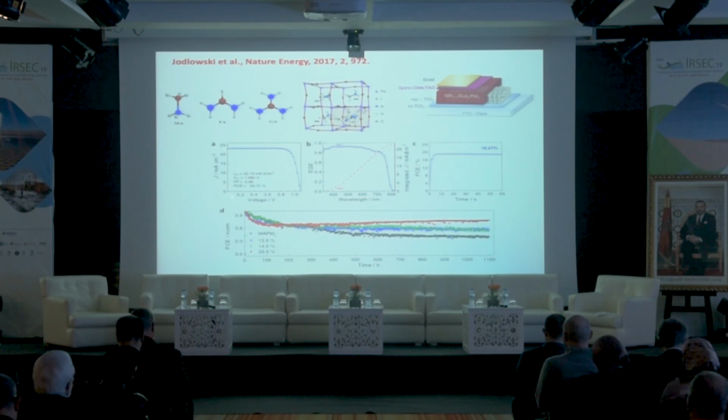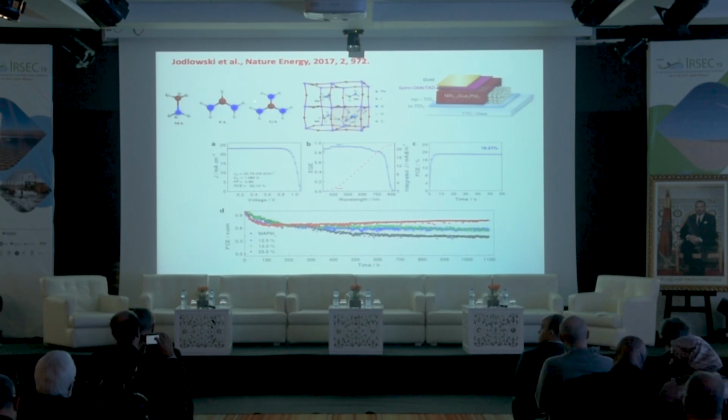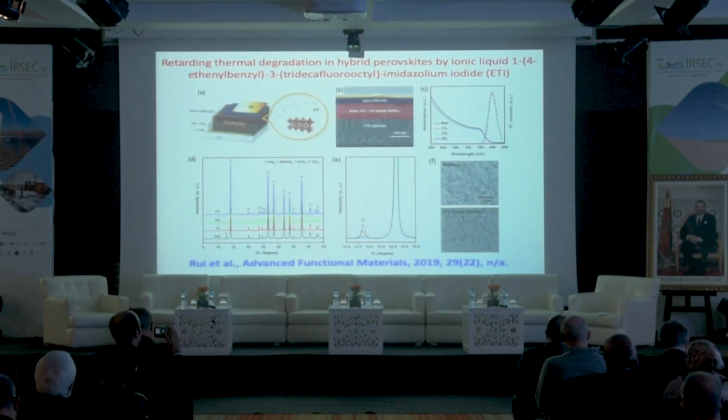However, the beauty of this material is when you have 25% of guanidinium, you can see the red line, it's extremely stable performance up to 1100 hours. This was published in 2017, and having this 25% of guanidinium enhances stability significantly. That's what we call compositional engineering.